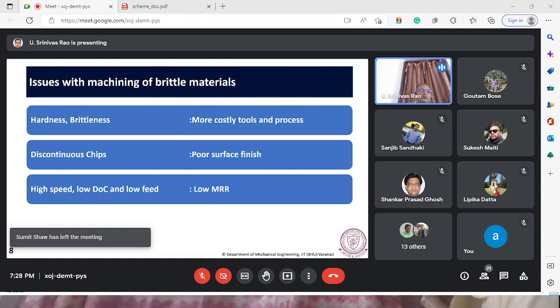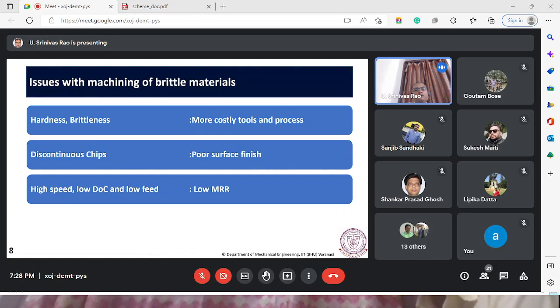Now, from this discussion, what we can summarize is that the main issues with brittle materials are high hardness and brittleness, so we need more costly tools and processes, and it gives rise to discontinuous chips which may lead to poor surface finish. And if we select these things, it will give rise to low material removal rates, but through this the process is feasible. So there is always a tendency to have low depth of cut and low feed, but to what extent can we go down, and still can we avoid this? Even at low depth of cut and low feed, avoiding this is difficult.